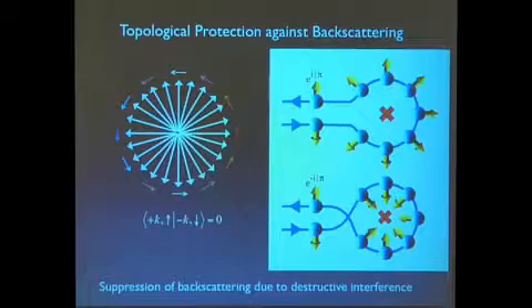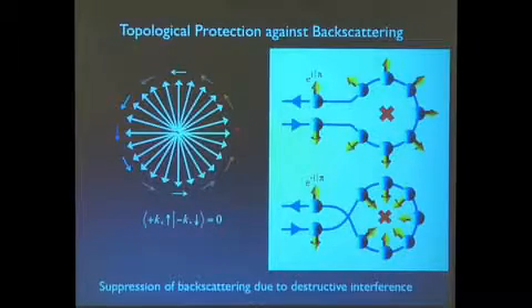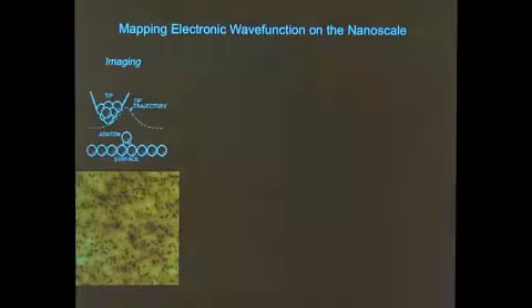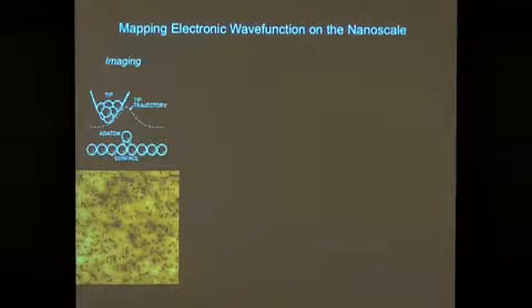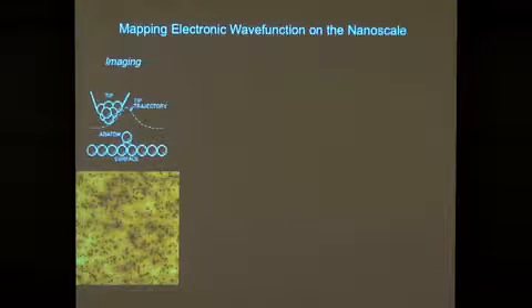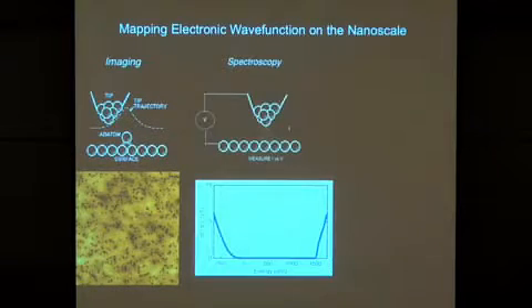So the first thing I'm going to tell you about are experiments which test this idea to see if this actually happens in an experiment. So how do we do this? Well, we use a scanning tunneling microscope, which, let me just remind you, you bring a sharp tip next to the surface to tunnel between the tip and the sample. You raster the tip across the sample. Typically, you keep the tunneling current constant, and you record the trajectory of the tip. That gives you an image.